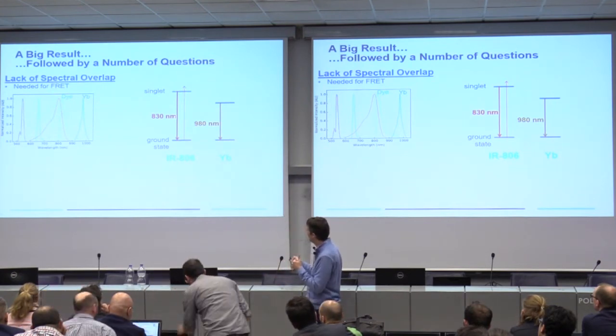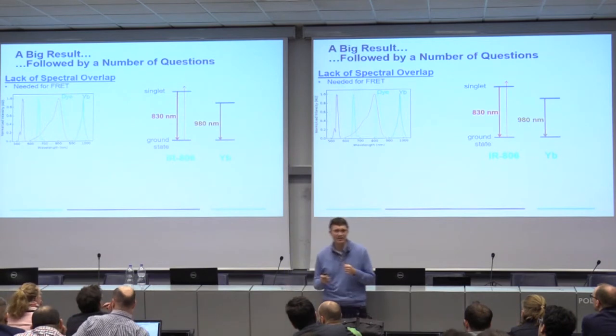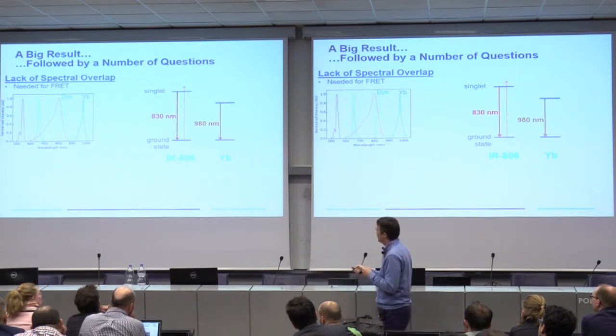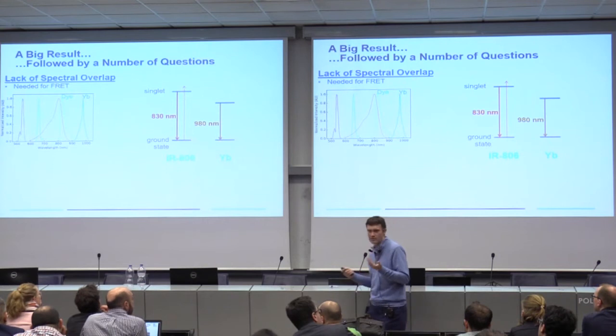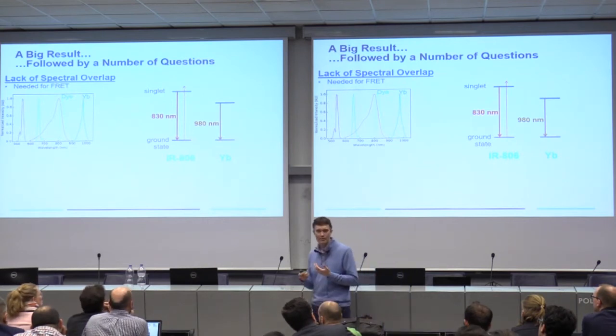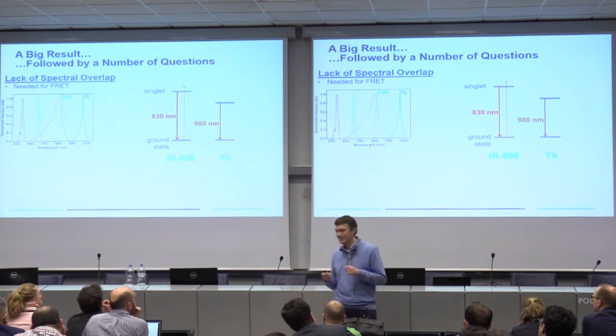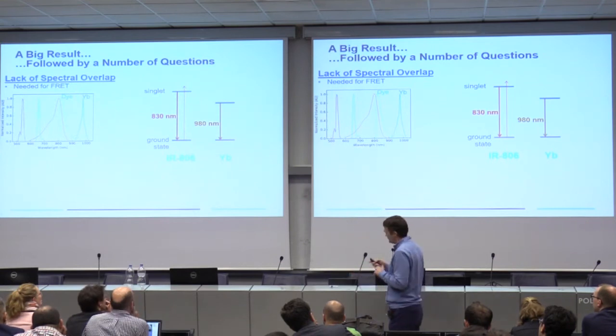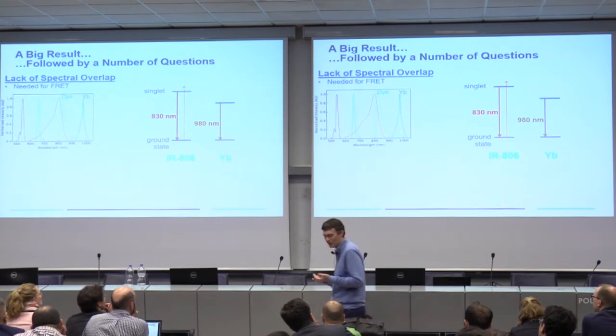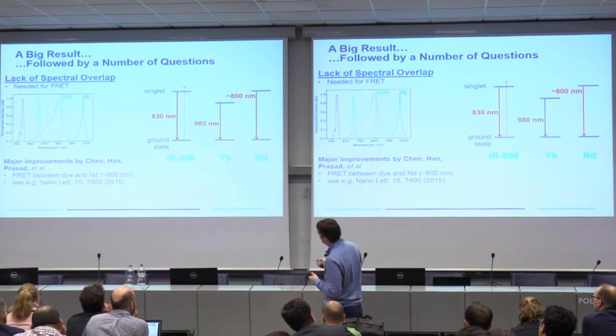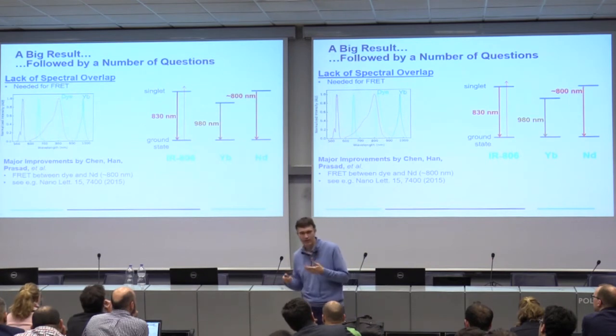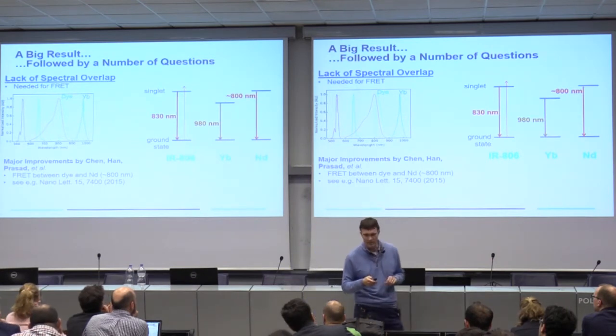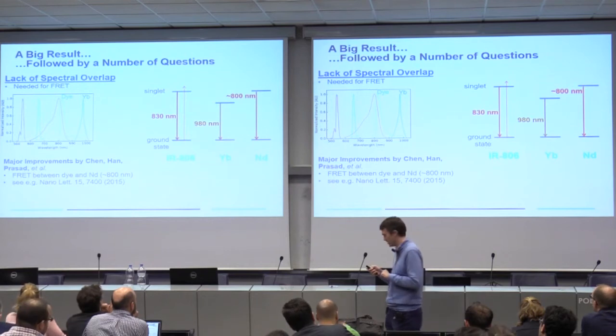The dye molecule absorbs and emits about 830 nanometers, and all the absorption in your upconverter absorbs at 980. There's basically 0 spectral overlap, and so all of your FRET equations told you that there's just no way this energy should be going into your particle. Why did it work? And so anyway, this led people to start looking into that, including us. Some people actually just changed the absorber in the upconverter to neodymium, which does absorb around 800, and they showed that they could get decent enhancement with that, but still not the big enhancement that these folks had got.